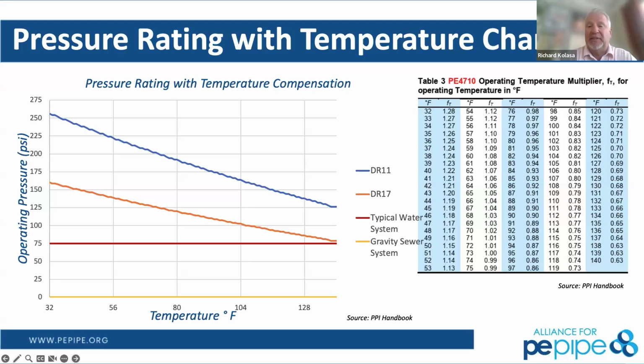So we have these calculation design coefficients that we can put into the formulas for determining what your pressure is. For example, if you had an operating system at 65 psi at 120 degrees Fahrenheit, you would see a reduction in that DR17 or DR11, but it would still be able to maintain that for the lifetime of the product. So know that you can calculate that, and that sometimes applies to the testing ability when you do your pressure testing, because let's say the pipe is hot or you're testing above ground where you're in a hot situation where maybe it sat all day in the sun and it raised the temperature. You can still test at that 1.5 or 1.25 or whatever pressure test your specification requires. So you just have to calculate what that maximum pressure is.